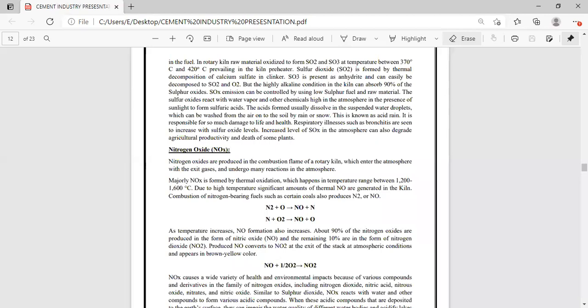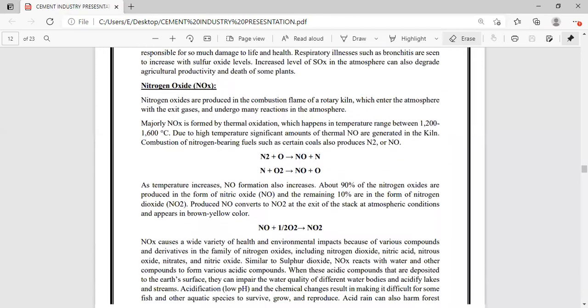Nitrogen oxide. Nitrogen oxides are produced in the combustion flame of rotary kilns, which enter the atmosphere with the exhaust gases and undergo transformation in the atmosphere. Majorly, nitrogen oxide is formed by thermal oxidation, which happens in a temperature range between 1200 and 1600 degrees Celsius. Due to high temperatures, a significant amount of thermal nitrogen oxide is generated in a kiln. Combustion of nitrogen-bearing fuels such as certain coal also produces NO, and this is the reaction. As the temperature increases, the NO formation also increases. About 90% of nitrogen oxides are produced in the form of nitric oxide, and the remaining 10% is in the form of nitrogen dioxide.